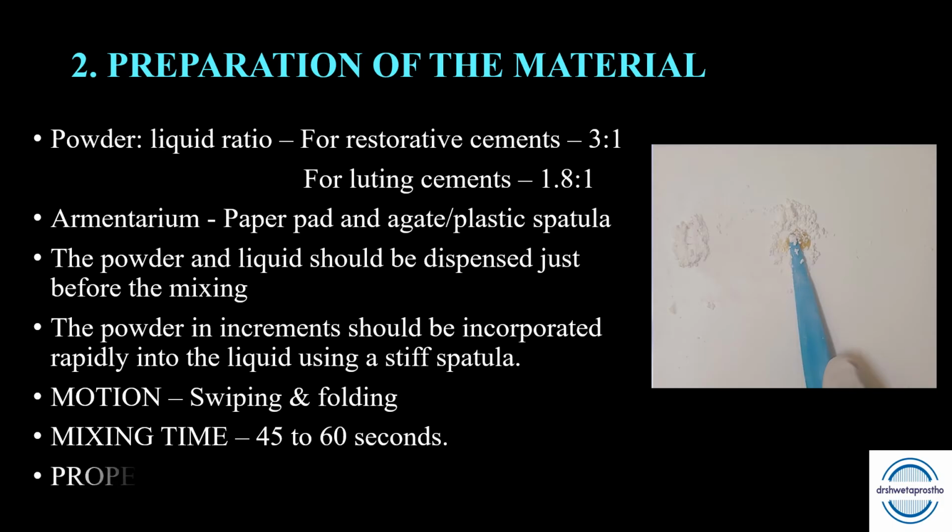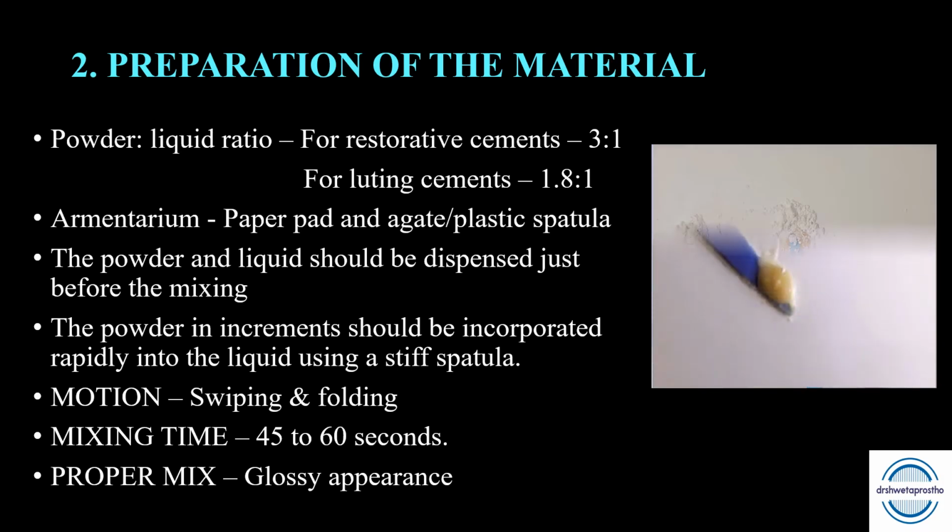Now when we are mixing, at this time the mix should have a glossy appearance, which indicates that unreacted polyacids are present on the surface. If it is a dull appearance, that means that inadequate free acid is present for bonding.